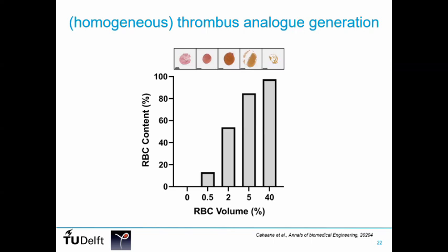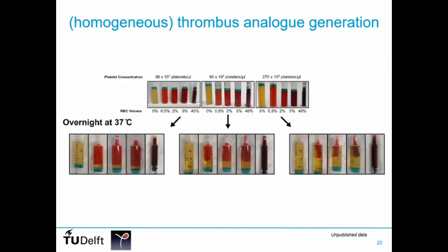If you go for a red blood cell suspension with roughly the physiological hematocrit, and you follow the procedure that we follow in our lab, of course that's not something that happens in your body, then you almost already have 100% concentration of red blood cells in your final sample. That was, of course, our initial experiments, where we did not look into the detailed effect of platelets.